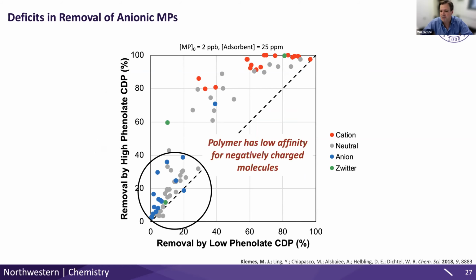However, not all pollutants are cations. In particular, the topic of today, PFAS: a lot of the ones that we care about the most, and that are hopefully on the precipice of being regulated more appropriately, are largely anionic. So things like PFOA and PFOS in the news, those were down here, and they're really not removed well by our polymers at all, even though the cyclodextrins themselves would seem to be good binding sites for them.